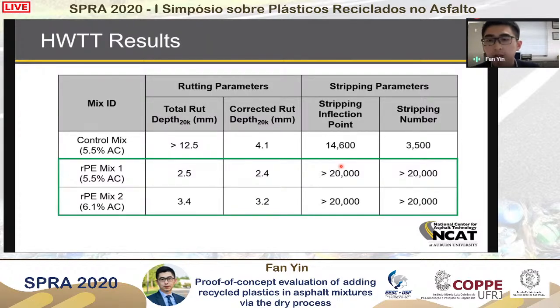Now if we look at the results here, those are the same three mixes I mentioned before. I'm showing two rutting parameters. For both parameters, a lower number indicates better rutting resistance, so keep that in mind. As we can see here, no matter which parameter we're looking at, the mixes with the plastics have a much lower corrected rut depth or total rut depth. That indicates better rutting resistance, which agrees with the high temperature binder rheological property that Dr. Morris mentioned before, and also agrees with the research that has been published in the past.